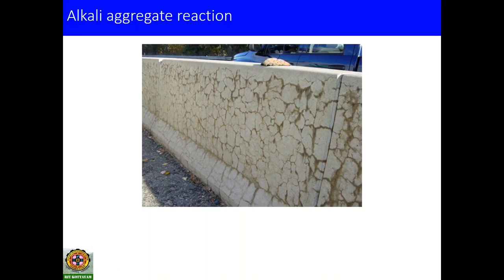So this typical map-like pattern is a signature cracking pattern of the alkali aggregate reaction. In the alkali aggregate reaction, if we use aggregates which have some reactive silica, like opal and chalcedony type minerals, it can react with the alkalis present in the cement, forming a gel-like compound, and this gel can absorb moisture from outside. Because of that, it is expansive in nature, similar to what happens in steel corrosion. The volume expansion happens, and it can crack. So that is what is happening in the alkali aggregate reaction.